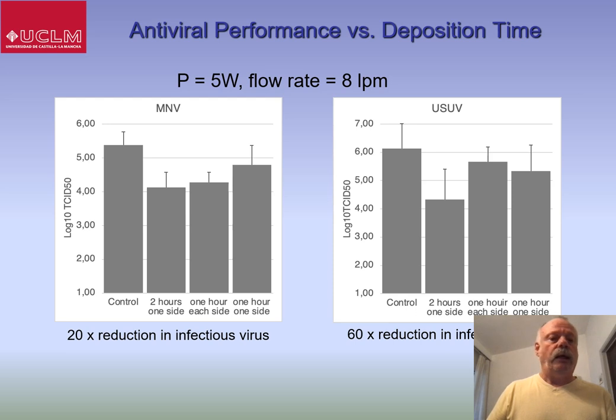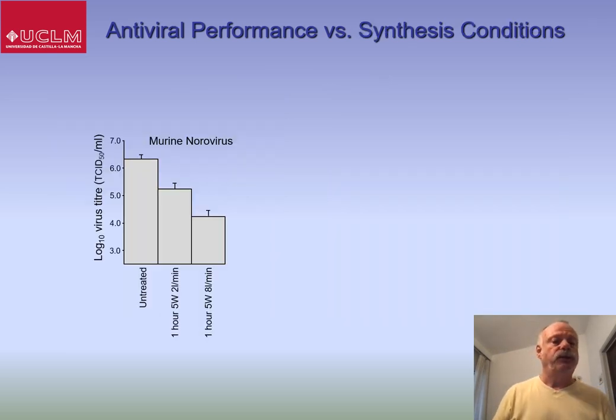If we look now at the performance as a function of the synthesis conditions, there seems to be an interesting trend here. In the case of the murine norovirus, what we're comparing here is the untreated cloth with 1 hour depositions with different source conditions. So here we've got 1 hour, 5 watts, 2 liters per minute, in other words, a low flow rate. And here we've got 1 hour, 5 watts, 8 liters per minute, high flow rate. And remember the effect this has on the nanoparticles: in the case of low flow rate, these are mostly single crystals, and on the high flow rate, these are mostly polycrystals. And you can see that there's clear improvement in performance in going from single crystals to polycrystals.